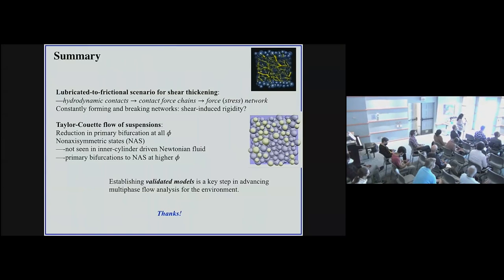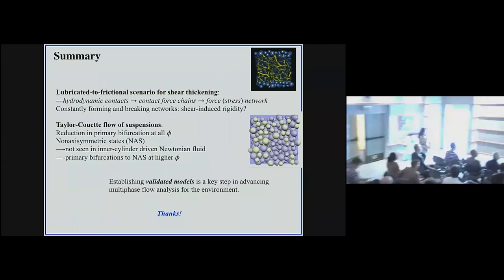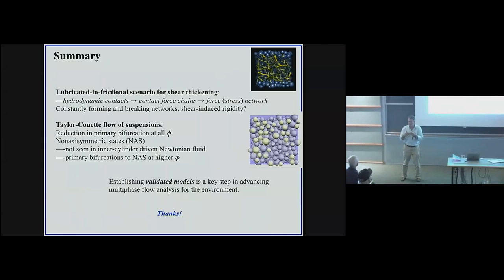And then I was curious, I wanted clarification about the rigid clusters versus just the clusters. How do you get that information out of your simulations? Like, what does that look like? Well, so we know the contact state of every pair of particles that are interacting with one another. And so that determines the number of constraints on their motion, depending on whether it's hydrodynamic, none. If it's a normal contact, 1, or frictional, then 2.